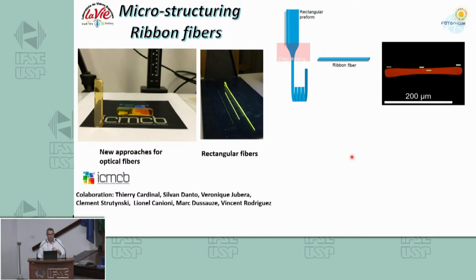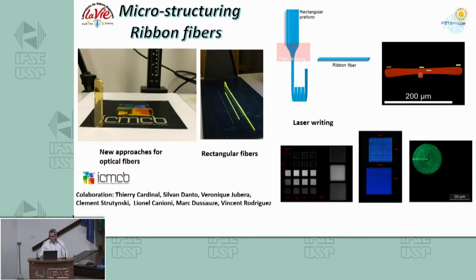And also, the last thing I'm going to say, using these materials, we can change a little bit. It's not an optical fiber, but a planar waveguide. So we call them ribbon fibers. Instead of having a cylinder preform, we can take a slice, like a microscope glass slice, put it in the tower and draw it. And then what do you have? We have a ribbon fiber, something like that in this dimension. So you can control the thickness of the fiber. And what is interesting with this, we can use a femtosecond laser to write patterns on the surface of these tiny fibers.